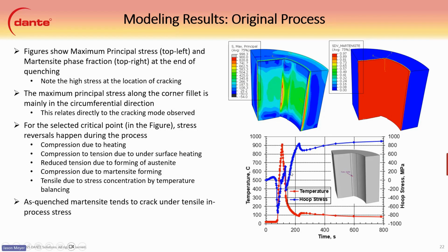And then when it's cooled and quenched completely, we see it goes back up to tension. It gets up to almost 800 or so MPa here, and we believe that's when the quench cracking actually occurs in the part due to the martensite phase. So that high tensile stress, based on the temperature rebalancing in the part, and the as-quenched martensite tends to crack under tensile process stresses. You'll be hearing that a lot today.